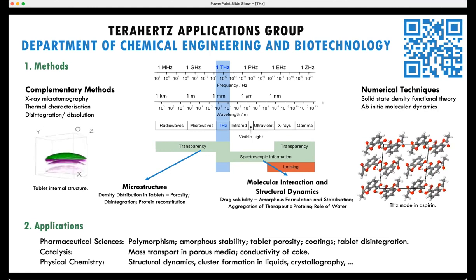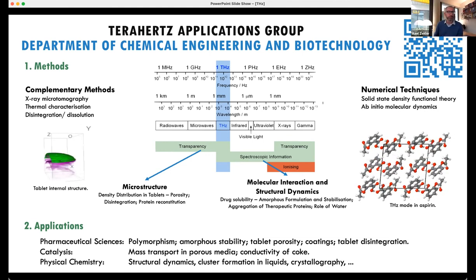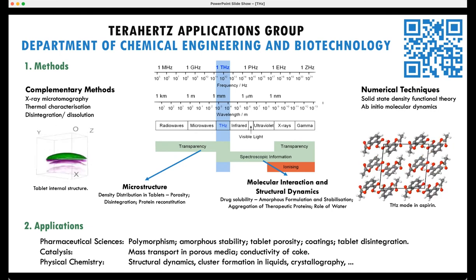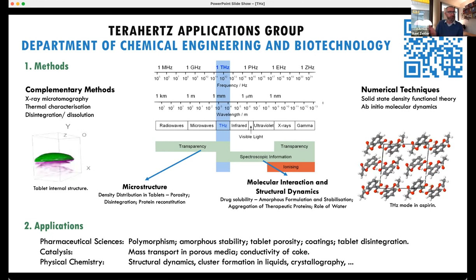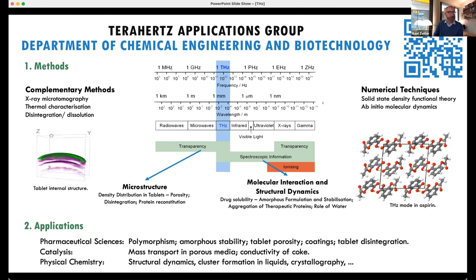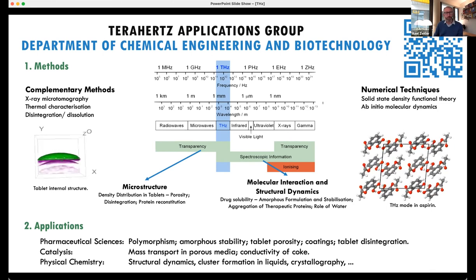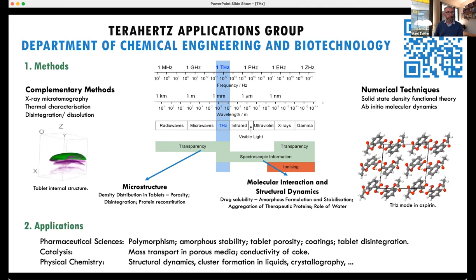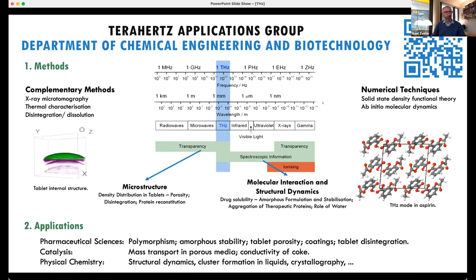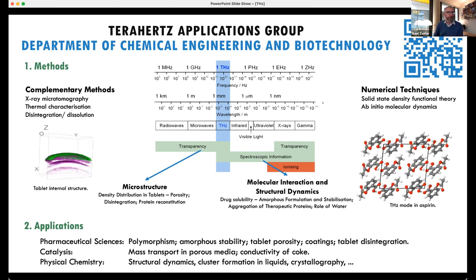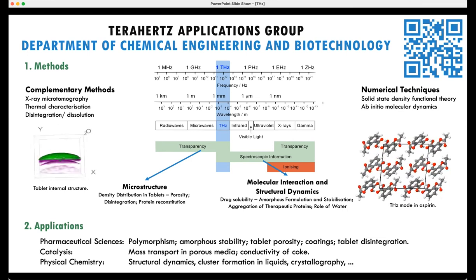I think about it as a complementary method to X-ray diffraction. In X-ray diffraction, you measure the average position of the atoms, but of course they all move around at room temperature or whatever temperature you are. And in terahertz spectroscopy, you measure the large amplitude motions that govern the cohesive forces of a crystal, essentially. Thank you.